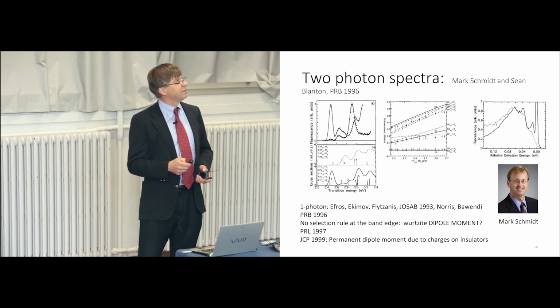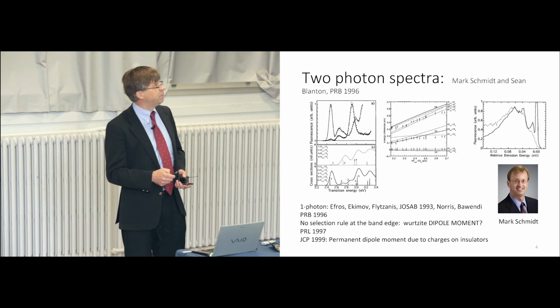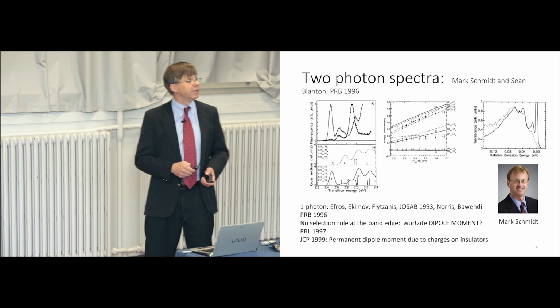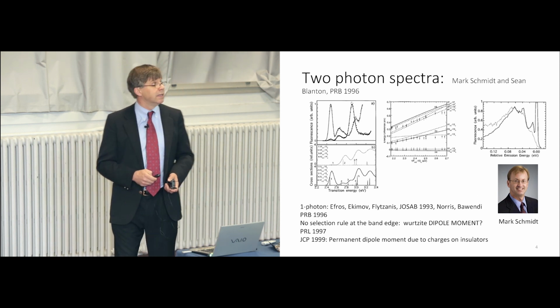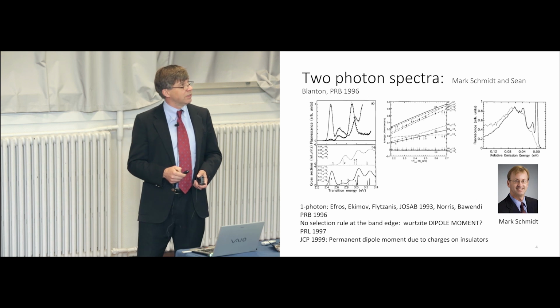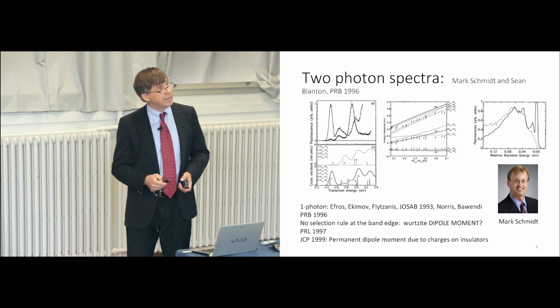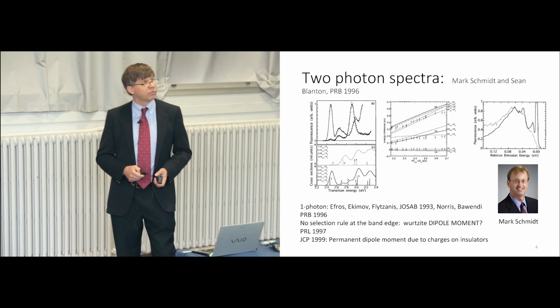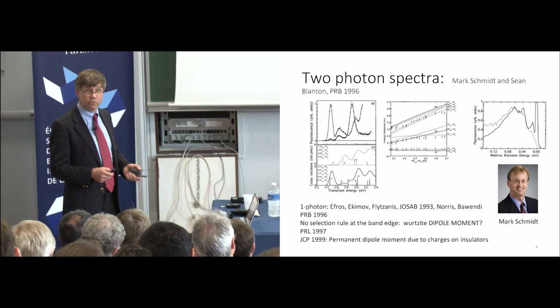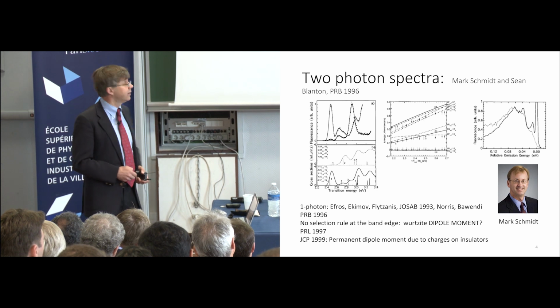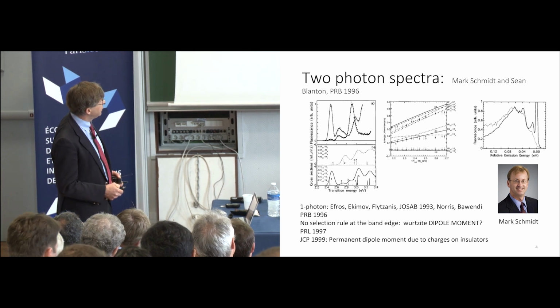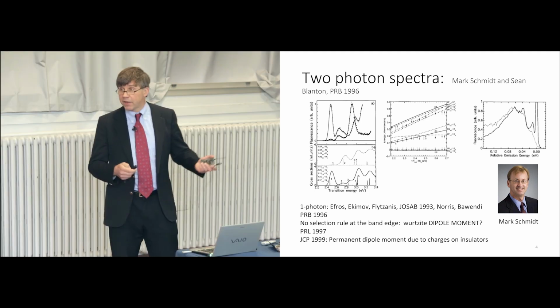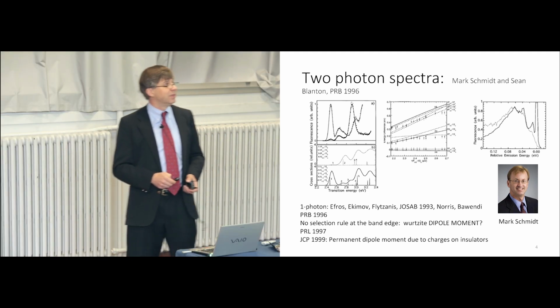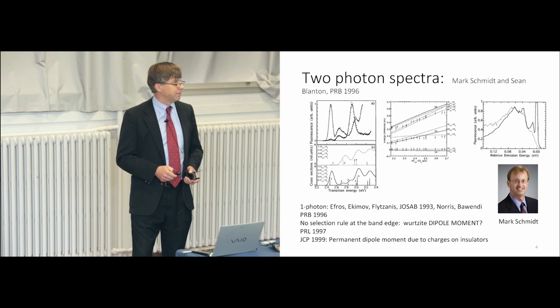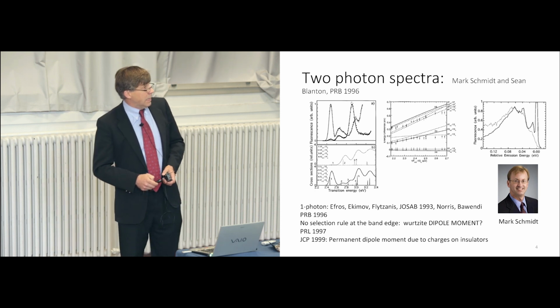This was a comparison of the one-photon spectra and the two-photon spectra. So you see they're very different. But the peaks kind of fall in the same place, even though they have very different amplitude. That's not that surprising based on the selection rule. What was interesting to us was that the near edge or the band edge features were very similar. So it didn't seem that there was a strong selection rule between an S-like transition or a P-like transition. And also you can see here the two-photon spectra has really no scattering line, which was our initial motivation to do two-photon single particle spectroscopy. Still an experiment that needs to be done.